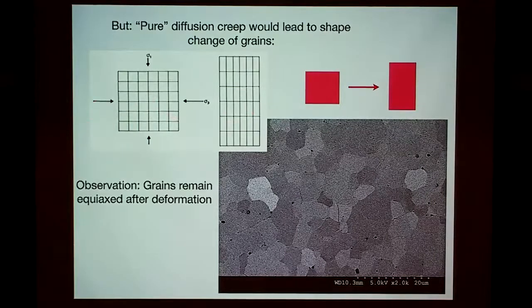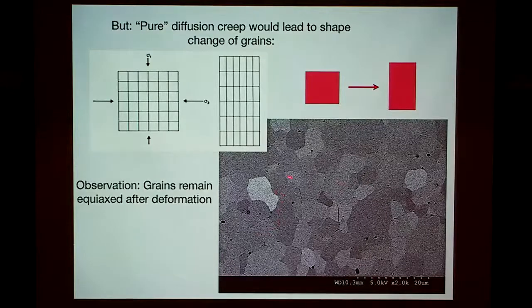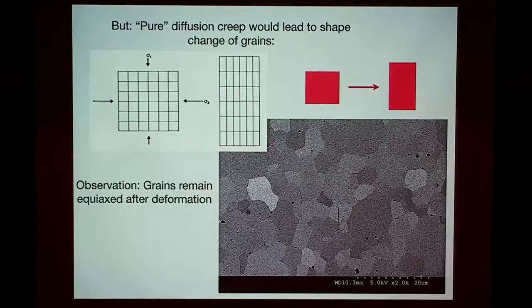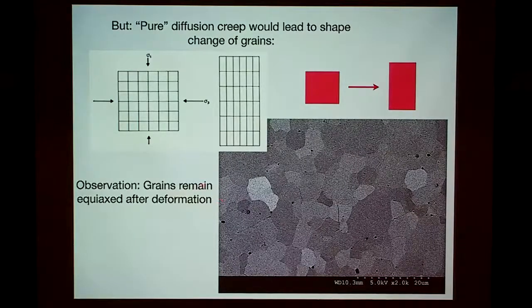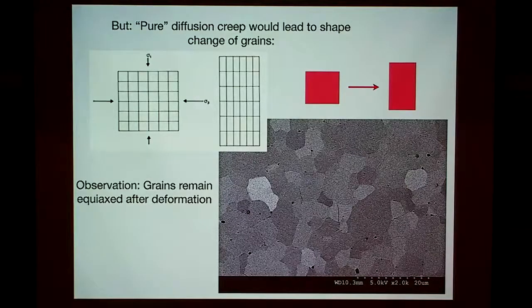In this scanning electron microscope image you can see orientation contrast — all olivine grains with exactly the same composition, different orientations giving a different backscatter coefficient. After considerable strain, the aggregate doesn't look like you'd expect — the grains actually continue to look equiaxed, about the same as before deformation. There was a question about whether different orientations deform in different amounts due to olivine's anisotropic elastic tensor.